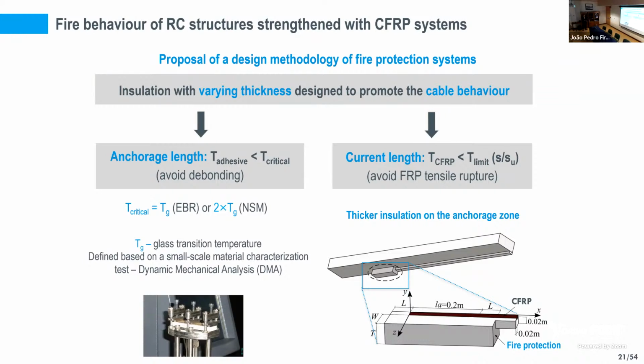And we proposed a very simple methodology, which was based on exploring that cable behavior that I showed you before, and the methodology can be defined in two main parts, let's say. For the anchored zones, the thickness of the fire protection, this thicker layer of protection, is defined based on critical temperatures that we also defined during my PhD. And the thin layer of protection for the central part of the system should be designed to avoid the tensile failure of the FRP material. The material thickness at that part should be designed so that a certain limit temperature is not exceeded, to avoid that tensile failure of the FRP that I mentioned before.